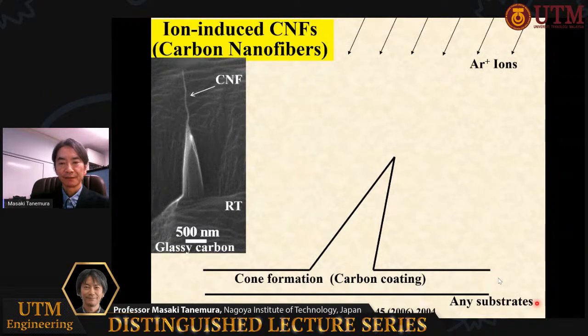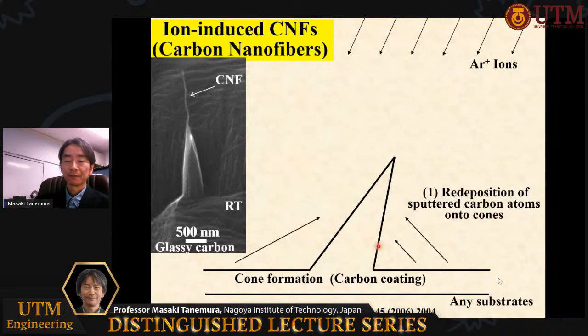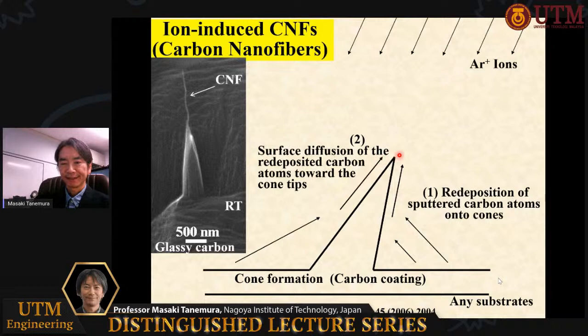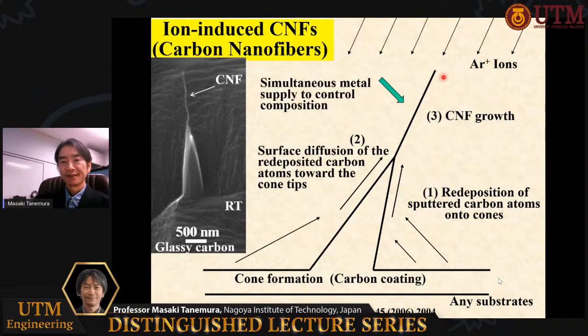This is the mechanism of the carbon nanofiber growth. Any substrate is okay. We use any kind of substrate coated with carbon. During ion irradiation, the well-known conical structure grows. Then, sputter-ejected carbon atoms are redeposited onto the cones. Then, surface diffusion of the redeposited carbon atoms toward the cone tips grows the carbon nanofibers. The carbon nanofibers grow without any catalyst and intentional heating. So, this is a room temperature process. Of course, if we supply any metals and semiconductors during the carbon nanofiber growth, we can control the composition of the carbon nanofibers.